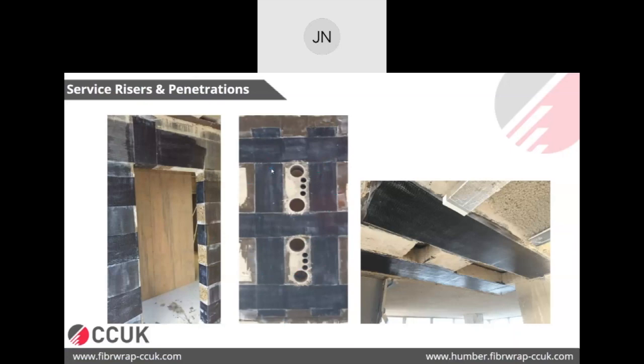So the concept behind here is that whatever rebar you're going to cut with these openings, you design FRP for the force generated by those rebars. So that's why you apply FRP first on all four sides, and then they cut these openings, so that as soon as you cut the rebar, the stresses will transfer to the FRP.